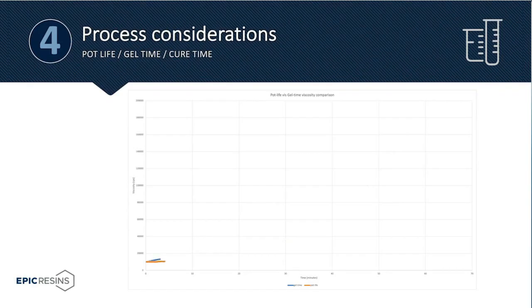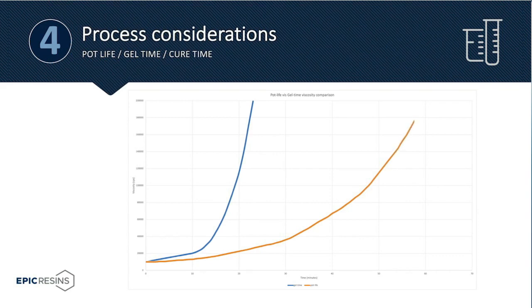For example, in this slide, you show two lines on this graph, viscosity versus time. In the first line, you see a very slow increase in viscosity until approximately 10 minutes, at which point the viscosity increases very, very quickly. This is a material that would have a very distinct gel time. Looking at the second line, you see a much slower increase in viscosity. This is a material that would have a specific pot life, or a time at which the material is no longer pourable or flowable in an application.